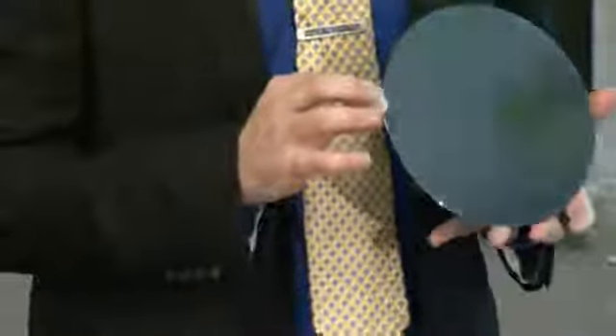Let's analyze it in a little bit more detail. So the front side surface is polished, right? Nicely polished. Polished to, I think, somewhere in the order of a few nanometers mean surface roughness, using a chemical mechanical polishing mechanism. The thickness is around 700 or 675 microns, somewhere in that range. It's a very, very thick wafer.